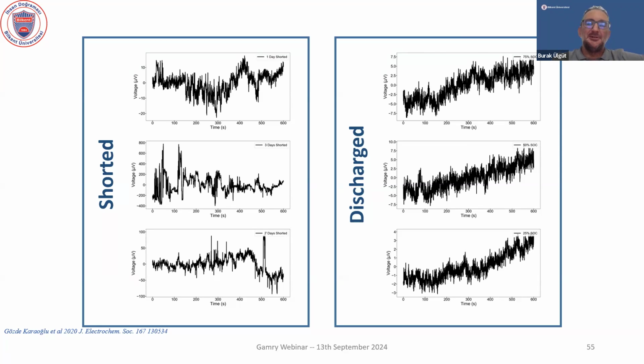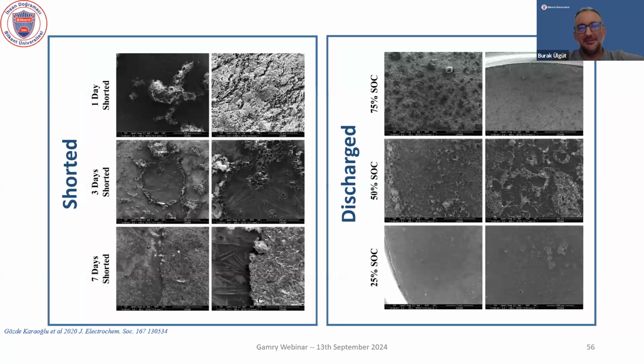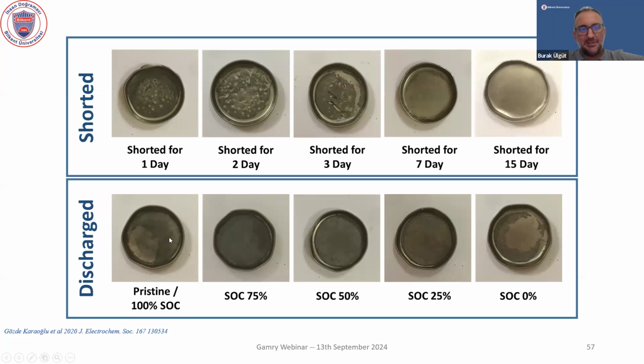And the reason for this, unsurprising in hindsight, is pitting corrosion. So when you discharge it slowly, as you can see, the metallic lithium actually dissolves, gets oxidized in a pretty uniform manner. So as the discharge level increases, it goes all the way down to the stainless steel current collector. When you short them, because it tries to do a lot of things in a very short time, the discharge starts happening at the defects. And you can see that this looks a lot like pitting corrosion. It gets worse. And these are not scratches that we made when we were opening the battery, by the way. This is exactly how the battery discharged. And then when it comes to 7 days, we are almost back to the stainless steel bare bottom electrode. So this is the reason for that increased noise during discharge.